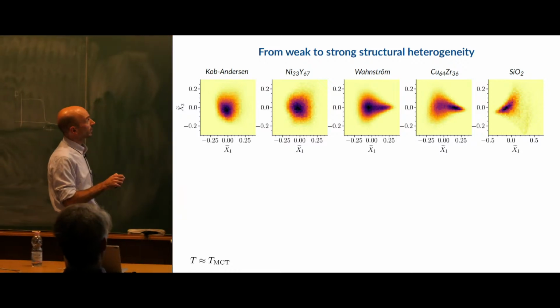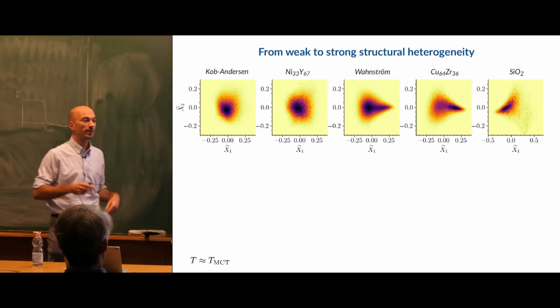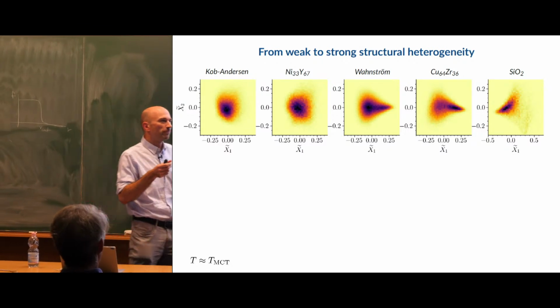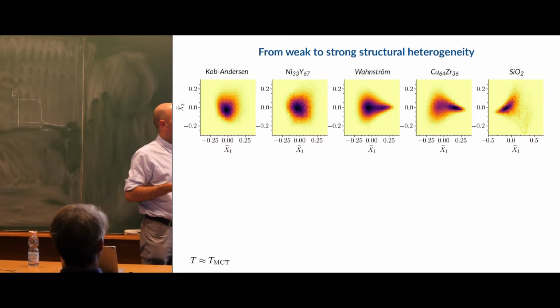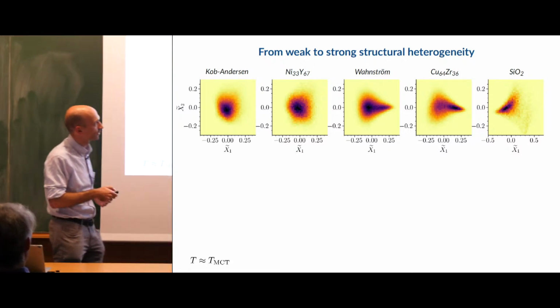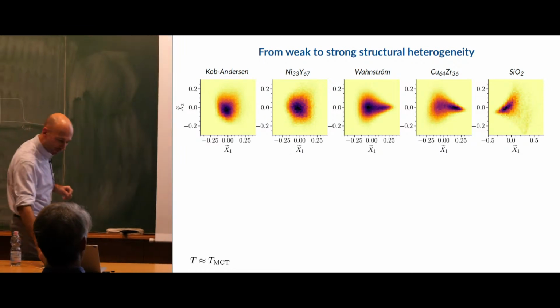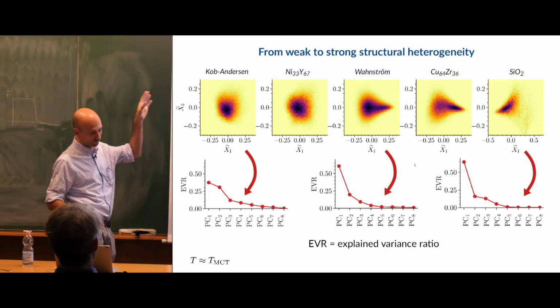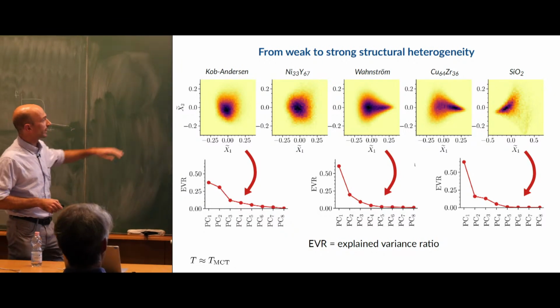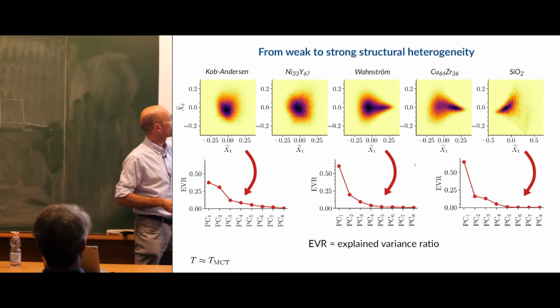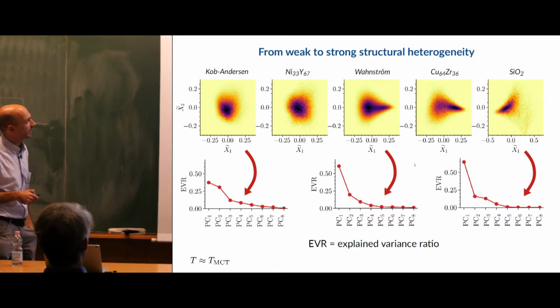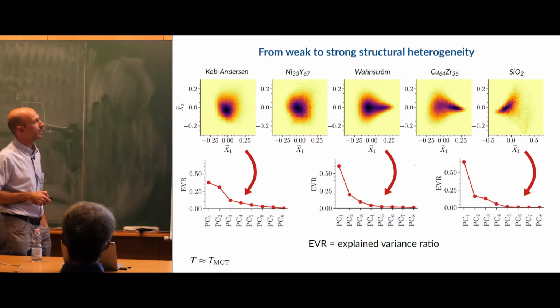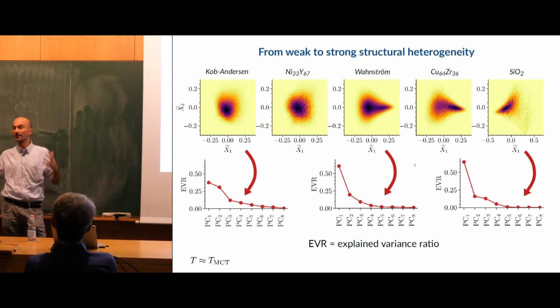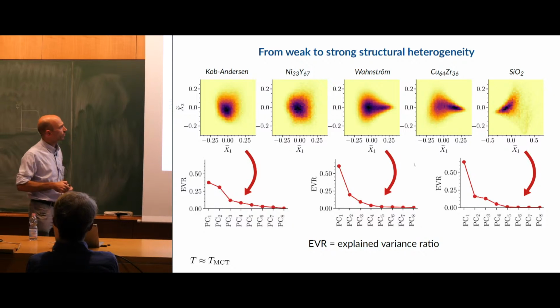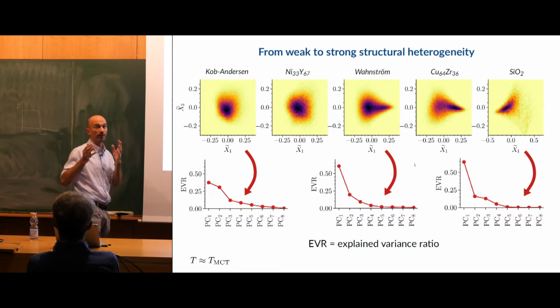Okay, so going from left to right, what I see is that there are systems that are weakly heterogeneous, in which there are no well-defined locally favored structures, and systems that are more strongly heterogeneous on the right. To argue that it's enough to look at just a few principal components, here I show the captured variance along each of these principal component directions. We see that with just 1 or 2 principal components, we already gather a lot of the variance in the full data set. And there's usually a gap between the first 2 principal components and the rest. So it seems like it has a relatively low intrinsic dimension.